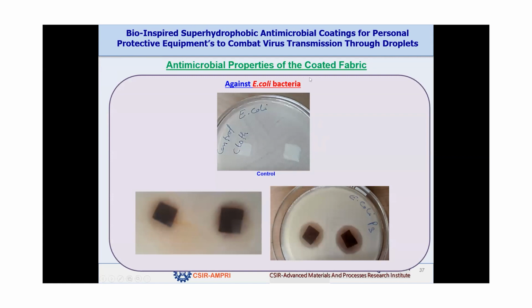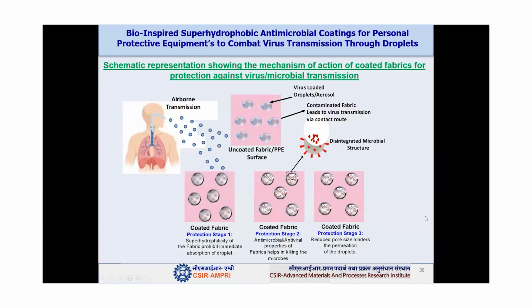And this is the antimicrobial property of the coated fabric. We have got results for only one strain yet, E. coli, which is a very common pathogen responsible for infections. You can see here, once we put the fabric, there is a clean zone. That means the bacteria got killed by this fabric, which is a very interesting result.